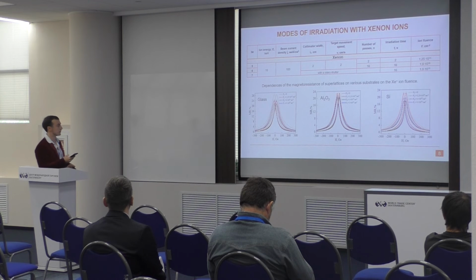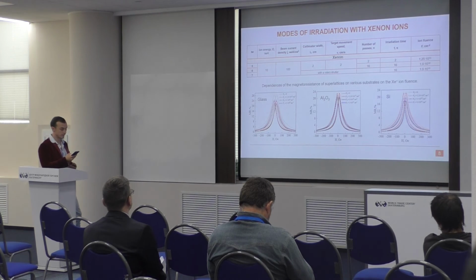all types of substrate. The graph showed that the magnitude of the hysteresis of the magnetoresistance of cobalt, iron, copper superlattices practically does not change, despite a strong change in the shape of the magnetoresistance curve, and is approximately 38%.